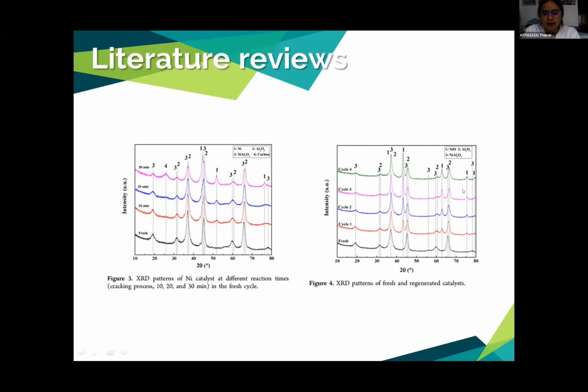This slide shows the XRD pattern. In figure 3, the XRD pattern at reaction time shows that the peak of carbon occurs at 30 minutes of runtime. And in figure 4, the XRD pattern compares the regenerated catalyst with the fresh catalyst. We found that the peak of nickel alumina decreases and the peak of nickel oxide occurs. That means nickel alumina changed to nickel oxide, and the effect on catalytic activity is that it stopped.